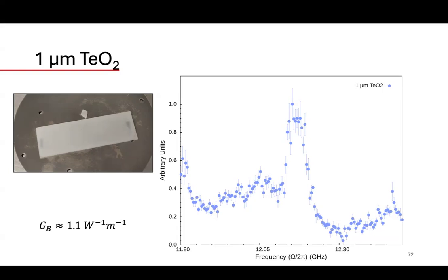However, through writing my dissertation and re-evaluating data deeply, I looked deeper into the process of physical vapor deposition and deposited films, and the amorphous nature of deposited films, the grain sizes of tellurium dioxide that would certainly result in a larger dissipation rate of deposited tellurium dioxide as compared to its crystalline counterpart.